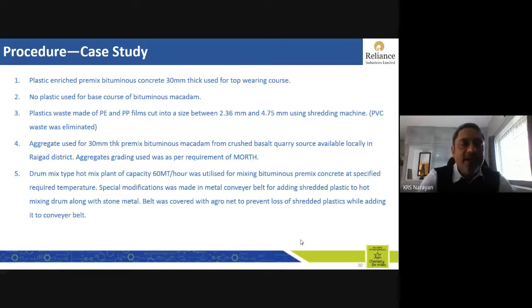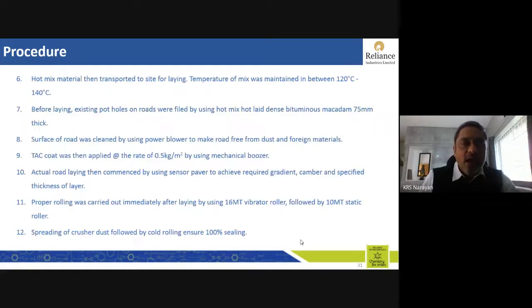That was eliminated. So the aggregate used was locally sourced from Raigad district, and then as per the requirement of the MORTH standards. The drum mix capacity of 60 metric ton per hour was utilized for manufacturing the plastic coated mix, and then mix was transported to the site conventionally as per whatever the road contractors do, and then the temperature was maintained between 120 and 140 degrees Celsius.